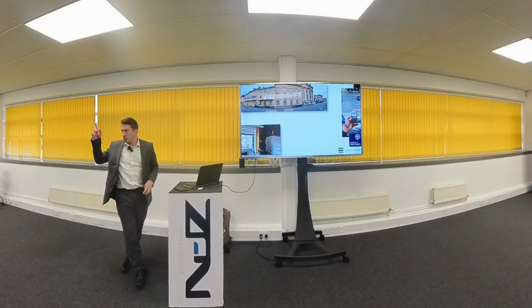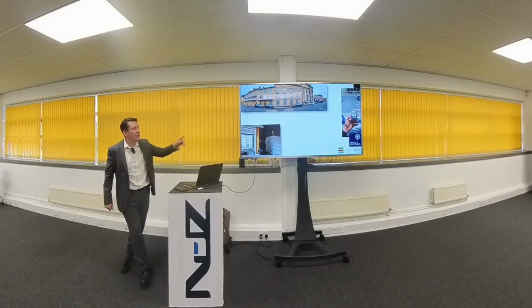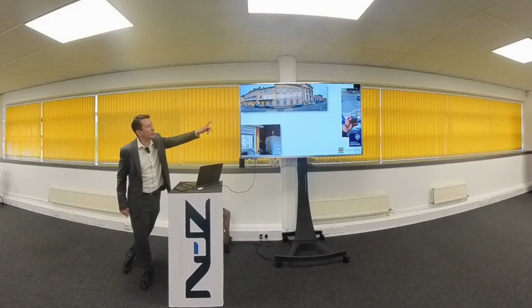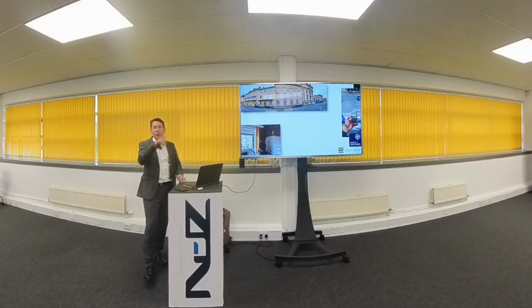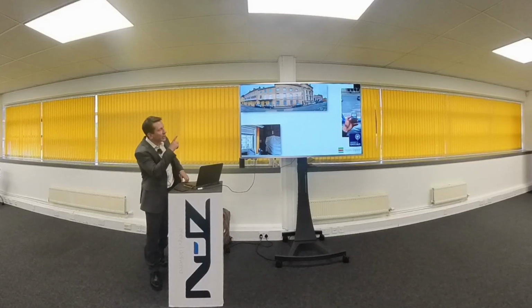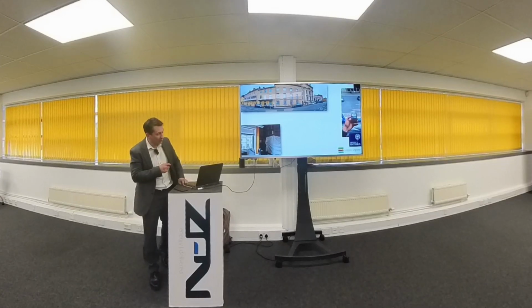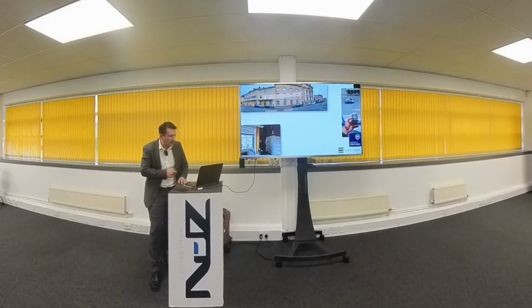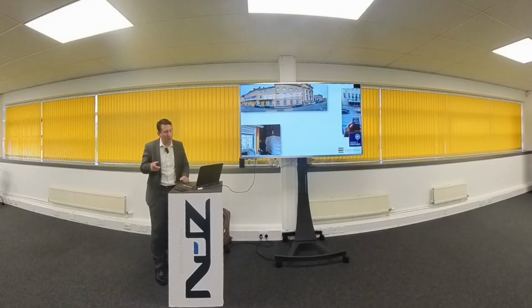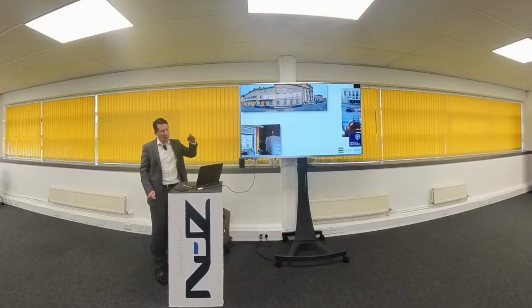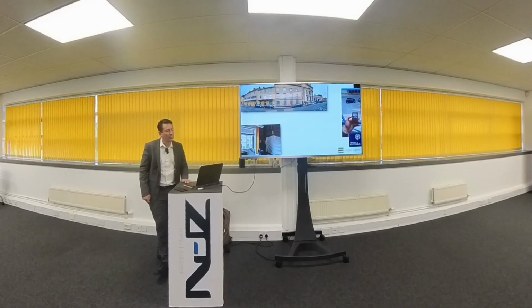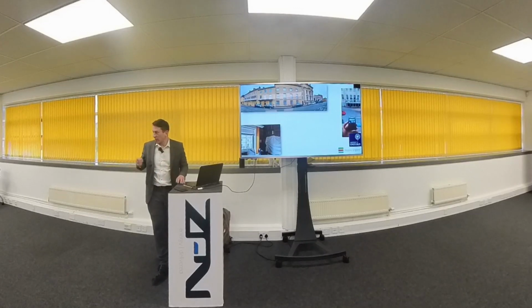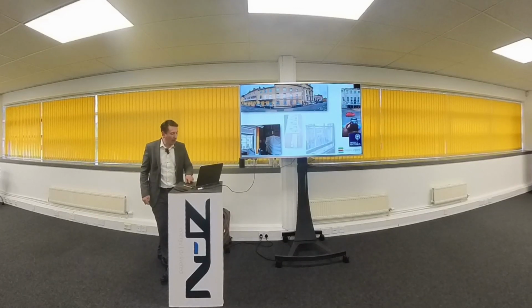Interestingly, we've got a demonstration which we can show later in terms of energy saving. This is a solar meter, the wee video on the side. It's measuring energy through glass. It's a single pane. I might have to just describe it, but when the video starts, I'll just mute that. So it went from 139 watts per square metre down to 30. So that's with the coating above and not below. So that's the amount of energy going through the glass. We've got thermal imagery camera images and other things which we can demonstrate.